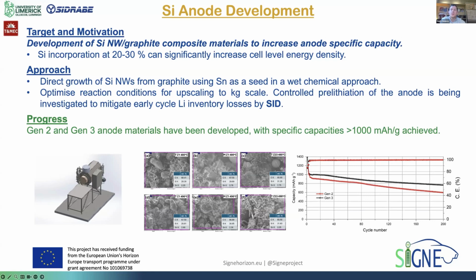So we can reproducibly make silicon graphite composite materials with up to 30% silicon content. And what you're seeing here, just as high level electrochemical performance, is our generation 3 material has 30% silicon and our generation 2 is around 25%. So essentially we can tune the silicon content within our anodes, and we've now been able to deliver anode materials that have capacities over 1,000 milliamp hours per gram.